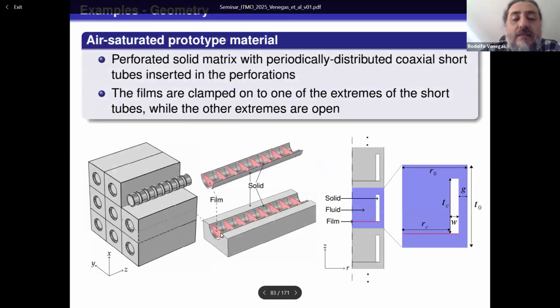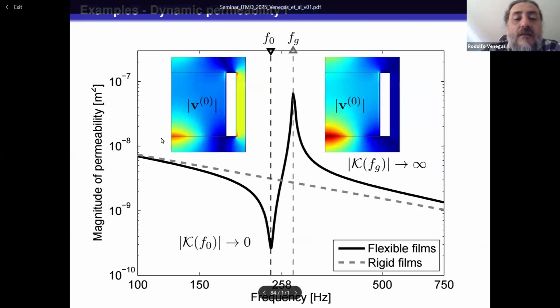In this case, this is, let's say, a little drum with one plate on one side and open on the other side, and it's an array of them. So this is a perfectly rigid solid frame. This is the fluid, and in red is the film or plate. So at low frequencies, the material with flexible films behaves just like the material if these films were perfectly rigid.